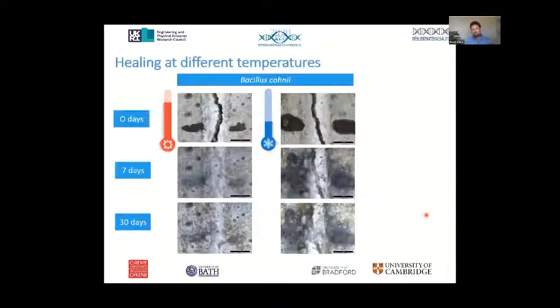So we've taken a long look at this aspect of performance, and this slide here shows bacteria-based self-healing of cracks in a mortar at both 20 degrees C and 7.5 degrees C using one of our normal mesophile bacteria, Bacillus cohnii. What you can see is that the healing was superb at 20 degrees C, but less than satisfactory at 7.5 degrees C, which basically confirms what we thought was happening.